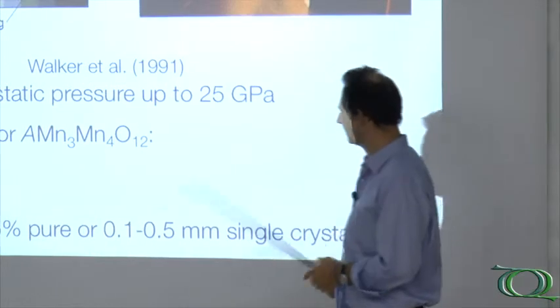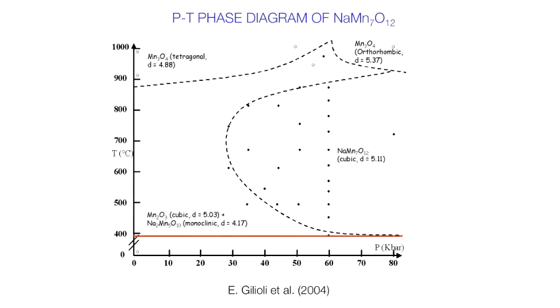You have 300 to 400 milligrams typically for this situation. It's quite comfortable for various types of measurement. We obtain either single crystal or sintered powders with some impurity which we could not avoid, but basically limited to 4 or 5 percent. Just to show you a phase diagram which has been studied by my colleague with a lot of experiment.